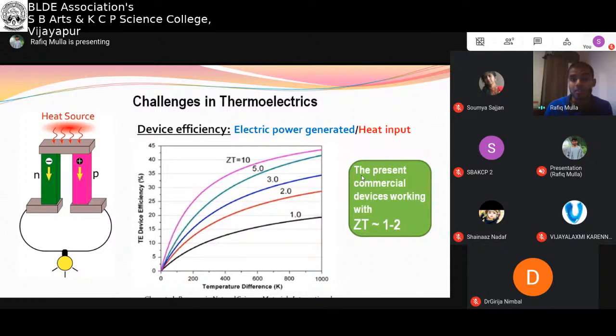So the challenges, there are mainly two challenges. One is very low conversion efficiency, as you can see from this figure. This is thermoelectric device efficiency for different temperature gradients applied to the device. Gradient means the temperature of the hot side minus the temperature of the cold side. So under different temperature gradients, we can see there is a different efficiency from the devices. Presently we have commercial devices which are working with ZT 1 to 2. These curves are for different ZT values.